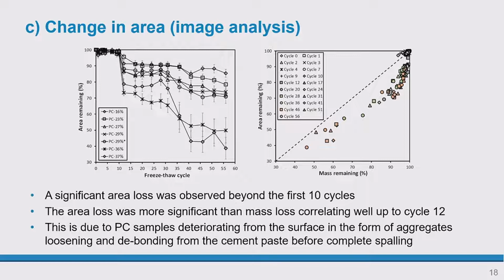And this is just a plot showing the change in area with freeze-thaw cycles. You can see that typically after 12 cycles, the mass changes dramatically, because that's when the cement paste becomes weaker and cannot take any more pressure, and it spalls away from the aggregates and damages the pavement surface.